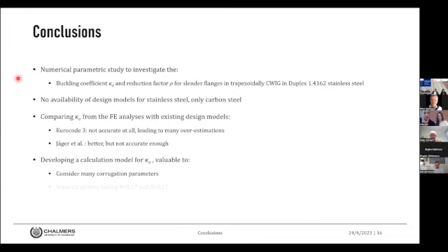To conclude, what we presented was a numerical study to investigate the buckling coefficient and reduction factor for slender flanges in trapezoidal corrugated web girders in duplex 1.4162 stainless steel. And that is due to design models being developed for carbon steel and not stainless steel. Comparing the buckling coefficient from the finite element analysis with the method of the Eurocode showed that the Eurocode is not accurate at all and leads to many overestimations. The model of Jaeger et al. is better, but is not accurate enough. So in developing a new calculation method for the buckling coefficient, it was shown to be valuable to consider many corrugation parameters, which was taken into consideration.